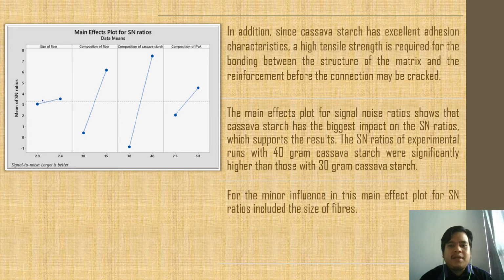Second, the main effect plot for signal-to-noise ratio shows that cassava starch has the biggest impact on the SN ratios, which supports the results. The SN ratios of the experimental runs with 40 grams of cassava starch were significantly higher than those with 30 grams of cassava starch. The minor influence in this main effect plot for SN ratios included the size of the fiber.